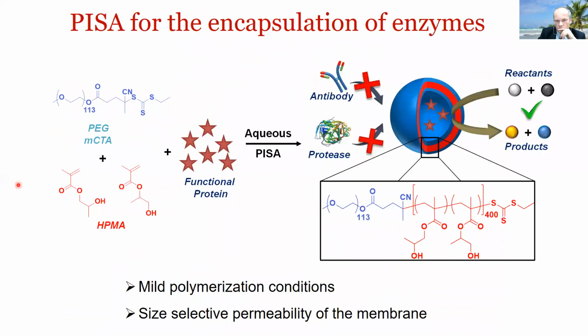So the concept being that if you imagine we take a PEG macro-CTA, which has a RAFT end group, we then polymerize just HPMA. It commercially comes as two different isomers, but we just polymerize the commercial mixture. You can imagine doing this polymerization under mild aqueous PISA conditions, say with photo initiation, with a functional protein, and then with your protein embedded within your construct, it's protected from antibodies and proteases, but the size selective permeability of the membrane allows for reactants to permeate and access the enzyme and products to diffuse out, so you can still retain the functionality of the enzyme when embedded within the construct.